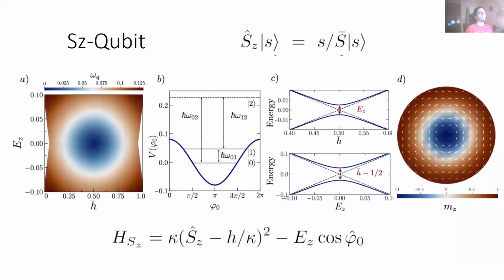So in here, they made it possible to learn if we can get this structure anharmonic, like we mentioned before, and how we can lift the degeneracy in energy relationships of these two parameters, because there are two parameters that affect the Skyrmion's behavior, which are the magnetic field gradient, which is supplied by the micromagnets, and the other one is the out-of-plane electric field.